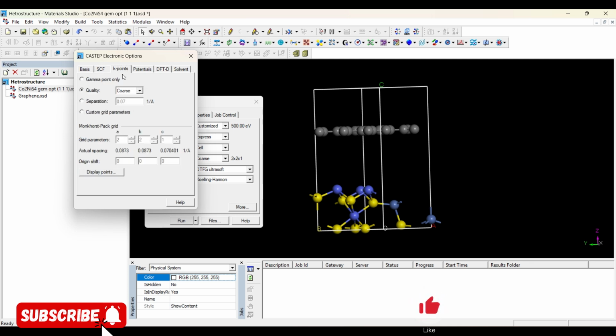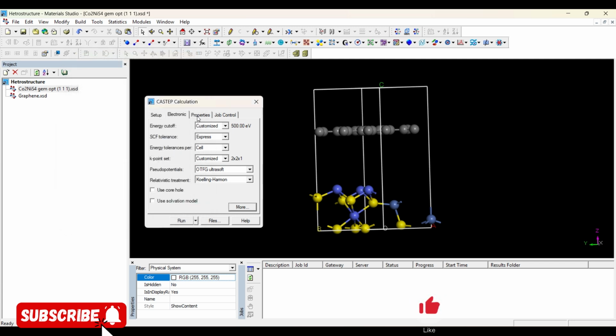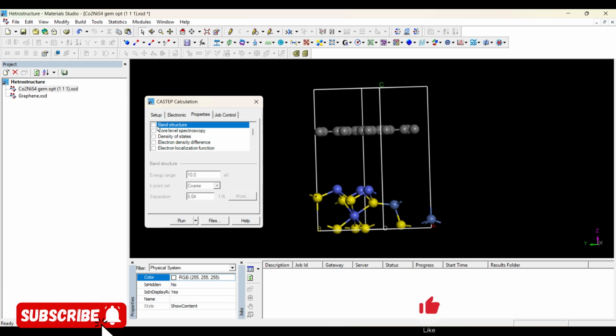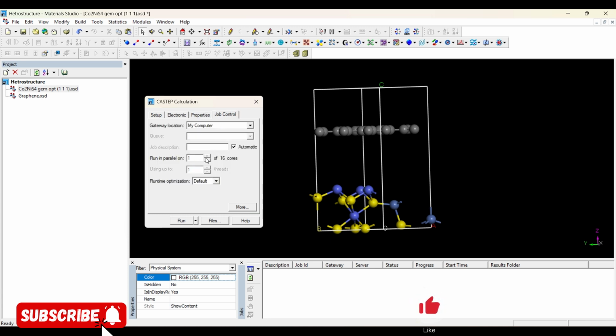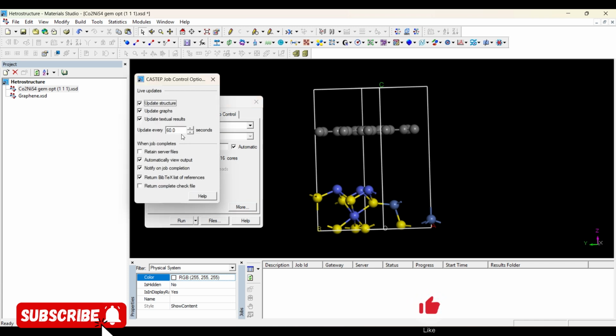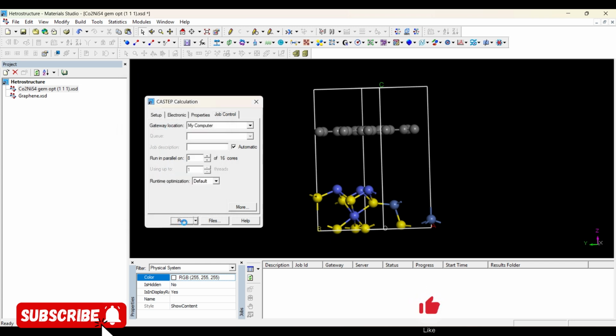K points, could use custom K point as we are doing on Espresso. 2 2 1 is okay. Properties, we don't need to check any properties here because we are doing geometry optimization, just population analysis is okay. And job control, I will be using 8 cores here. Go to more and choose 1 second here. Okay, this calculation will take a lot of time because as it is a heterostructure and there are a lot of atoms.